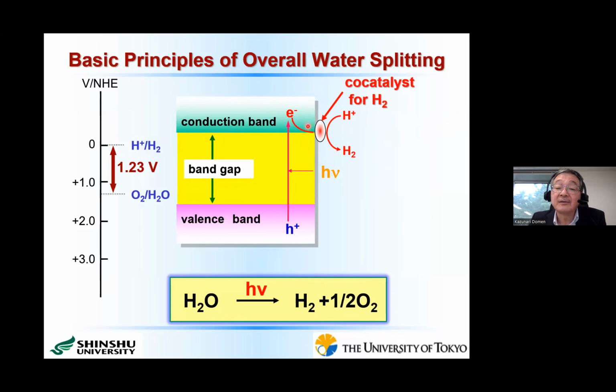However, as I showed here, in almost all cases, as far as we use an N-type semiconducting photocatalyst, we need to introduce a so-called co-catalyst for hydrogen evolution to facilitate electron transfer to protons and to generate hydrogen molecules.